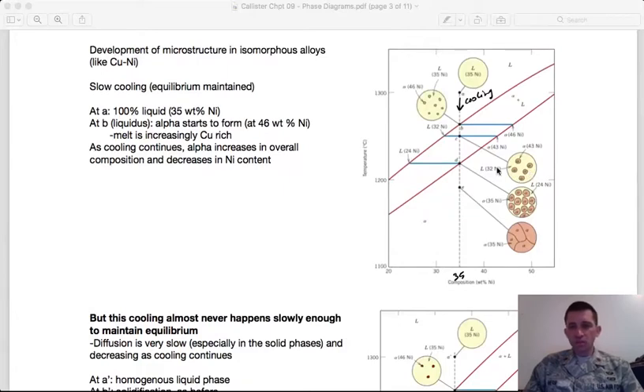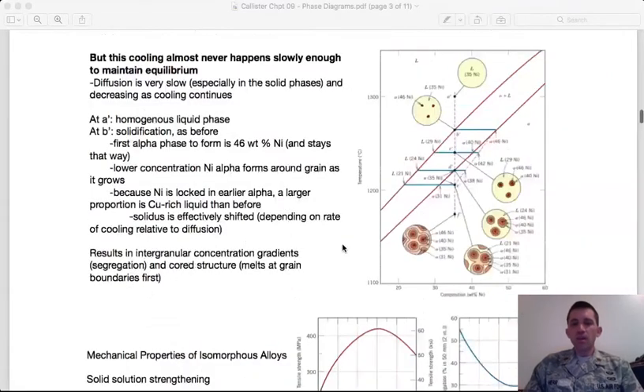I mentioned this cored structure. I may have gotten a little bit ahead of myself here. Remember, I said that this is equilibrium. So even though I'm solidifying at a higher percent nickel, the assumption is that the temperature is still high enough that as I solidify the next layer, that's a lower weight percent nickel, the higher percent of nickel in the interior is able to diffuse out and give me an overall composition of 35. However, that takes a long time,